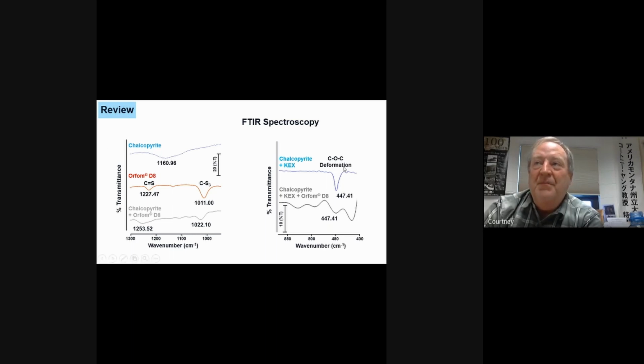And then we tried to look for the xanthate that's already on the surface to see if it would desorb. So here's the xanthate peak at 447.41 with KEX. So this signal, this COC bond, is coming from potassium ethyl xanthate. We put Orfom D8 in that system. If it does not desorb, then this signal should remain the same. It's not a very good spectrum, but sure enough, you're seeing a peak at 447.41, telling you that the xanthate is still on the surface. So Orfom D8 does not desorb the xanthate to depress the chalcopyrite.